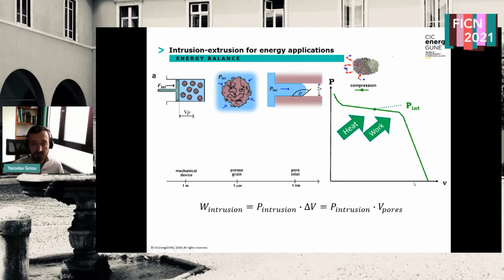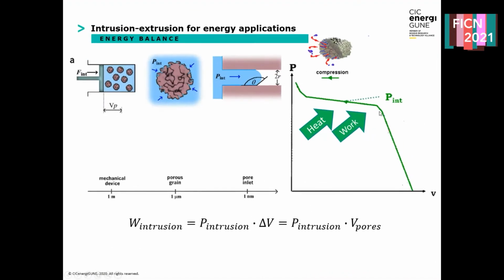So what's interesting about this system is that by reaching certain critical pressure, which we call intrusion pressure, the water can be forced inside the pore. So on the pressure-volume diagram, this is reflected in a plateau here, and this process is accompanied by accumulation of work of the system, which is intrusion pressure multiplied by delta V, which is the pore volume. But also, what is great about the system, is that intrusion is typically, not always, but quite often, an endothermic process. So actually heat is also absorbed by the system.